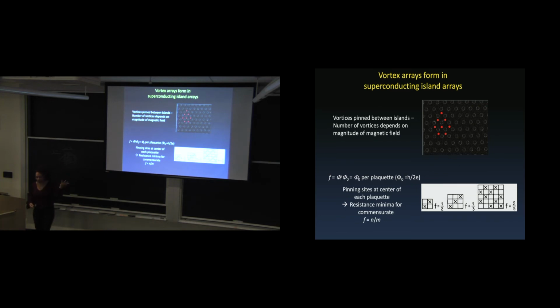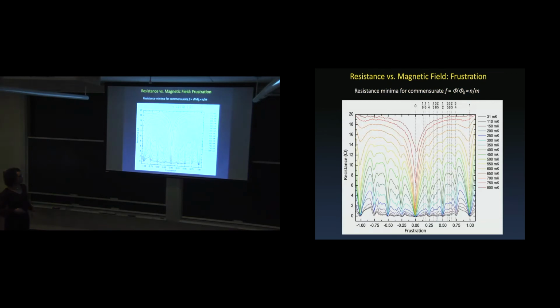Right? And so then I just measure resistance as a function of field for this sort of system, and I get data that looks like this. So this is resistance. And here I've actually put it in terms of frustration. Remember, this is just my field value, where here I have one vortex filling every plaquette between the islands. And notice what you see. At zero field, it's a dip. There's zero resistance, right?